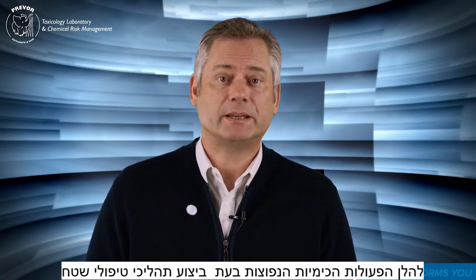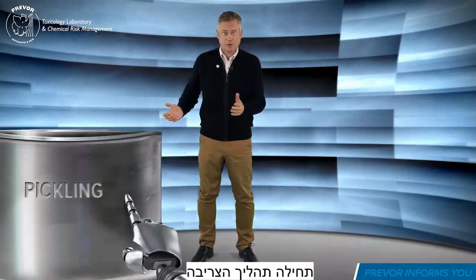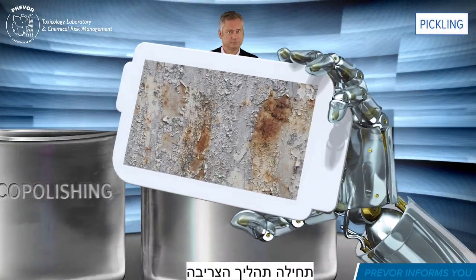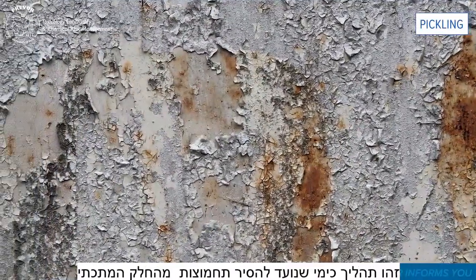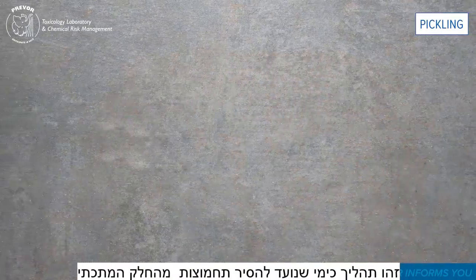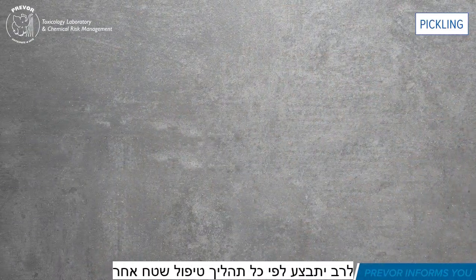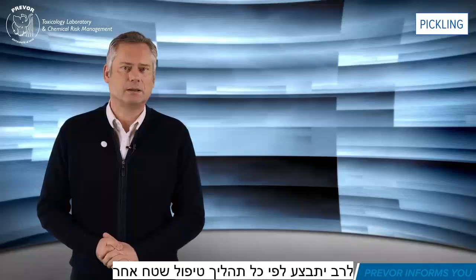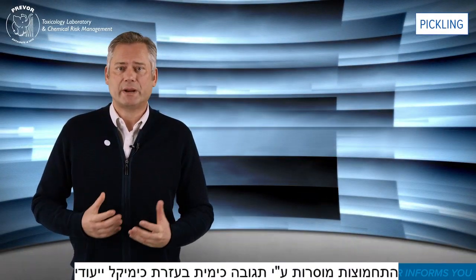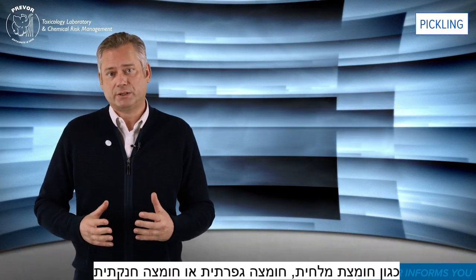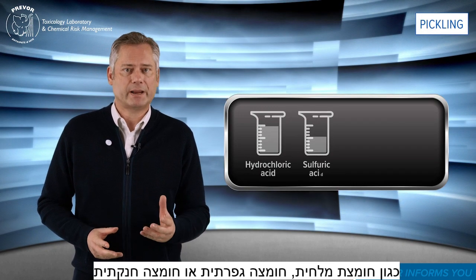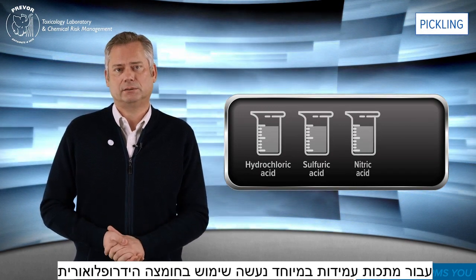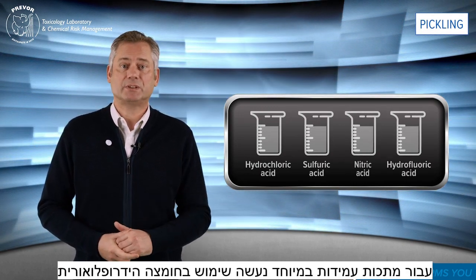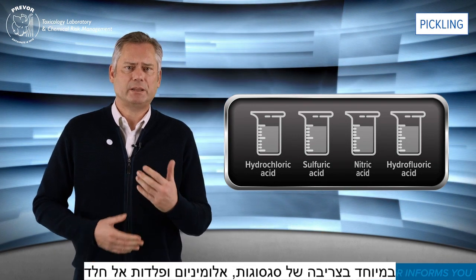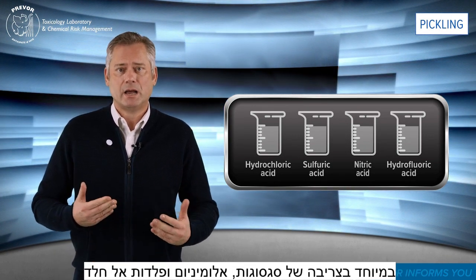Here are the most common chemical operations performed during a surface treatment. First, there is pickling. This is a chemical process used to remove oxides from the metal surface, usually prior to any other surface treatments. They are removed by chemical reaction with a pickling agent, such as hydrochloric acid, sulfuric acid or nitric acid. Hydrofluoric acid is used for some resistant metals, especially in the pickling of alloys, aluminium and stainless steel.